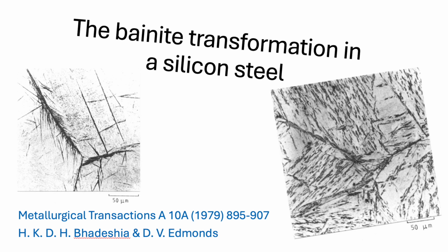Wow. So let's just quickly synthesize this. If you pull all the evidence together from this one carefully designed silicon steel, the picture becomes very clear. The kinetics, with those multiple TTT bays, directly contradicted the main diffusional theory, the solute drag model. Right. The upper bainite morphology, the high dislocation density, and especially that accommodation slip seen on the austenite planes, showed that physical shear and strain were integral to the process.